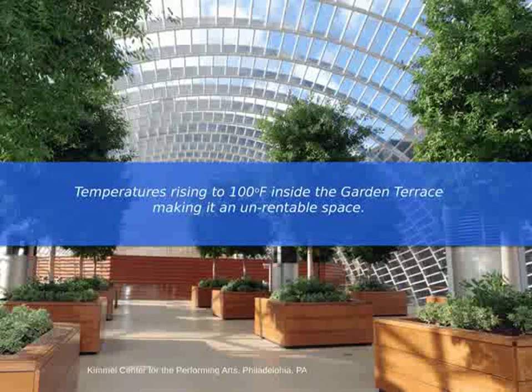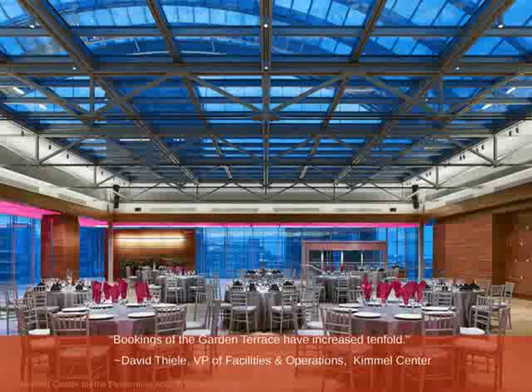And the idea was that they would have these gardens for events and for weddings, but because of the structure of this glass, the temperature rise was often up to 100 degrees Fahrenheit, so it was completely unrentable space. So the idea is that they came through and they came up with a solution. As you'll see, they actually reconfigured the entire rooftop garden and put up dynamic glass to create this beautiful wedding venue location.